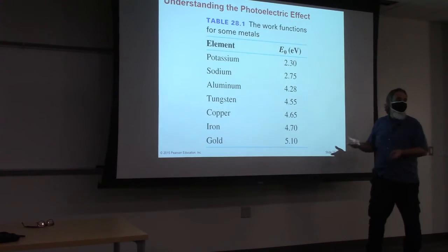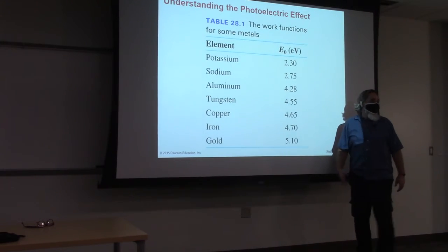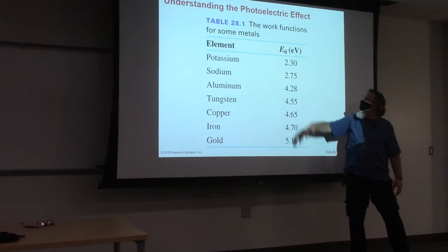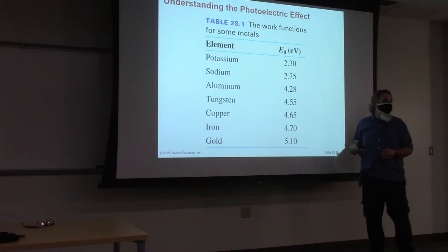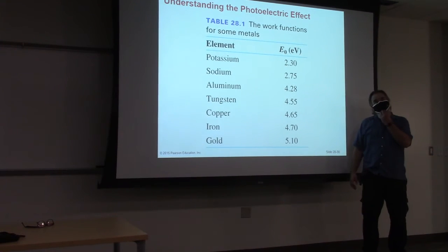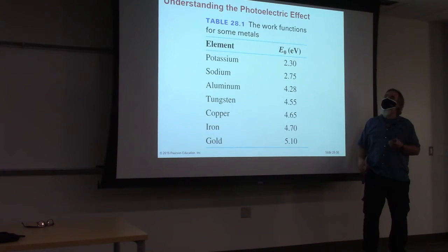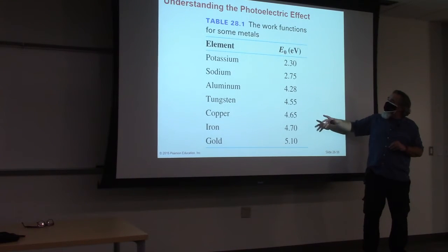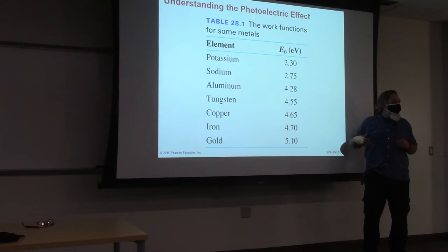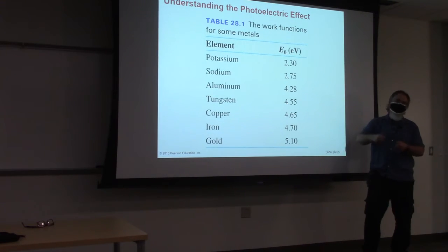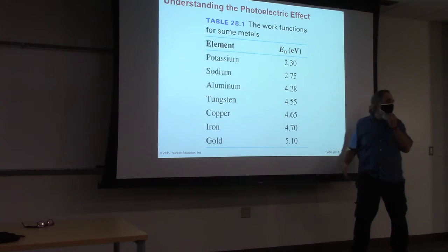There's no formula to really just say what it would be. They would probably get it experimentally, like just do the experiment, figure out what the work function is, and you can get that from the stopping potential, and then come up with a new number for that. That would be a good way to do quality control, really. Say you're building something and it's a mixture of gold and copper, and you want it to be mixed up this certain exact way. Measure what the work function is of that new alloy that you have. And then later on you're producing it in a mass way. You could grab a sample from the production line, measure it, see if it's really mixed up the way you thought it was mixed up.